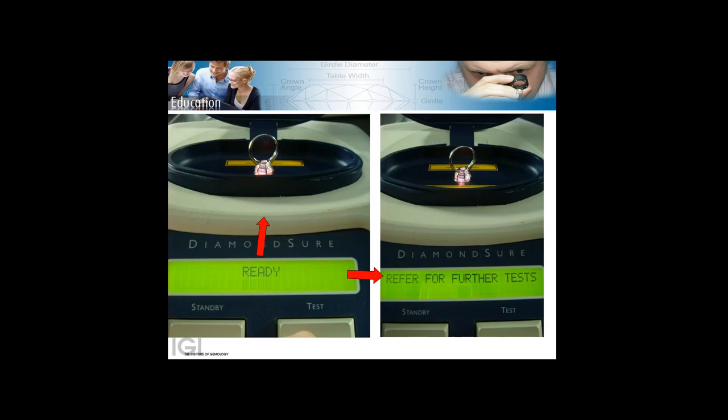That's how they divided the family of diamonds into two types, 1 and 2. So yes, all CVD diamonds are type 2A. The moment on the DiamondSure we see type 2A mentioned, we take it for further tests. Now, it doesn't mean every type 2A stone is a CVD stone. It could be a natural diamond also.